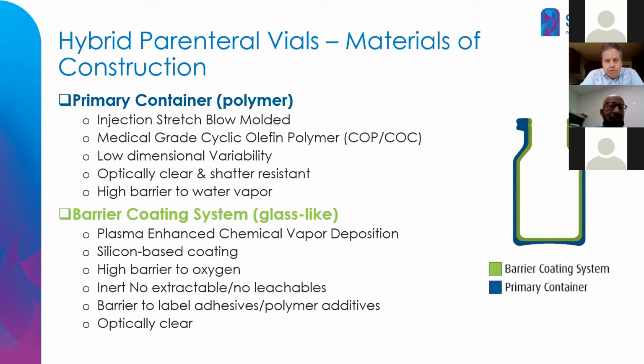Materials of construction, there are two components. The primary container is made of a polymer. And in the case of the vial, we injection stretch blow mold it. Injection stretch is similar to injection blow molding, but you have a smaller stretch ratio, and that helps us control the wall thickness of the vials. We use medical grade resins, and we focus on cyclic olefins, that's cyclic olefin polymer and cyclic olefin copolymer, COP and COC. These polymers have, with molding with them, very good dimensional stability, very good consistency so we can manage and keep tight tolerances. The containers are optically clear, and I think the important thing is that they don't break.